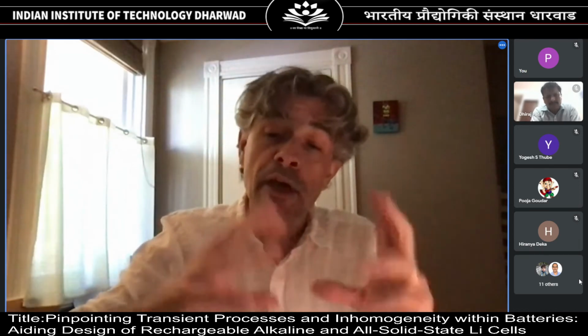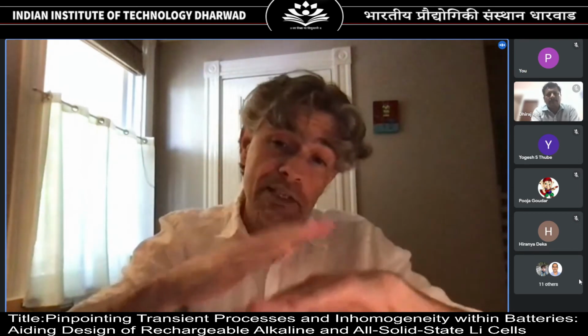So the layers, as you're cycling the battery, are constantly going in and out. And you have to imagine that these layers are in crystals that come together in these crystallites, and then the crystallites are agglomerated into a particle. As these layers at the atomic scale are getting angstroms closer together and apart from each other over and over, their volume changes. And so the volume of the particle changes while all of this is happening. Then these particles are packed together into a device, and the device has some compression on it. And so you have swelling inside the battery as you're cycling. This causes particles to fracture. So that's like a use failure as it's cycling.